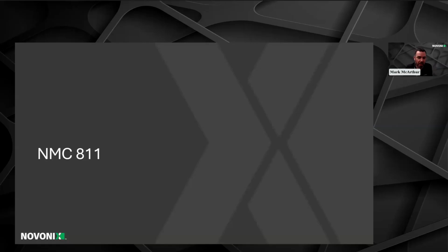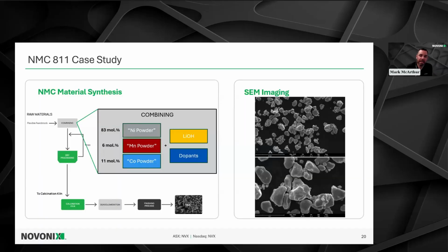My next example is on an 811 material, where we push the envelope a little further and increase the nickel content to 80% and beyond. In this case, we're talking about 83% nickel NMC 811. Very analogously to my last example, I'm combining 83% nickel powder with 6% manganese powder and 11% cobalt powder. Now, instead of using lithium carbonate, I'm using lithium hydroxide as well as dopants in a single step. And after conducting the all dry zero waste process, you end up having, again, these beautiful single crystal morphology NMC 811 particles.